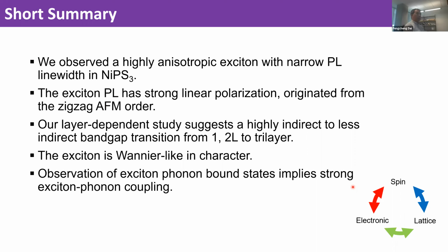Okay, Liang. Yeah, thanks for the talk. I have a quick question. When the sample is thin, how do you determine the a-b axes, and how do you determine the zigzag direction? Yeah, that's an excellent question. We do this in two ways. One is through Raman spectroscopy, because the axis of the Raman doesn't really change, you can always tell where the polarization is. The second is we also perform X-ray scattering to begin with to identify where these a and b axes are. And for the zigzag direction, you measure these a and b axes, and from neutron scattering, the zigzag is along this particular a axis.